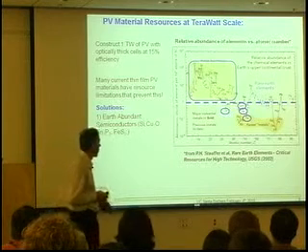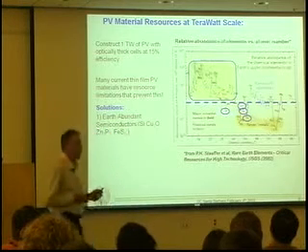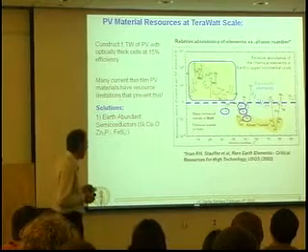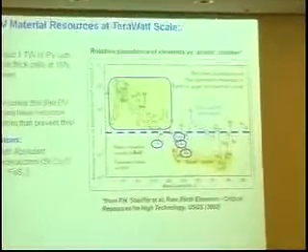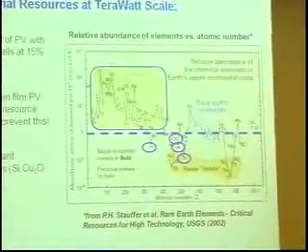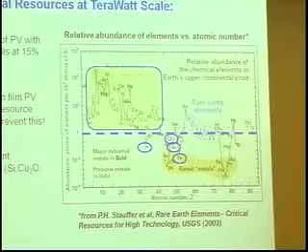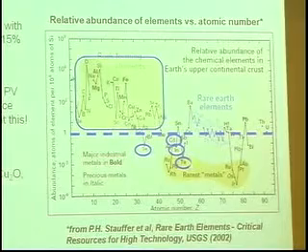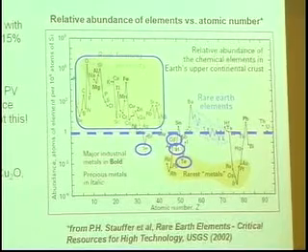There hasn't been a technological incentive to develop these materials, but there are a number of semiconductor materials that you can imagine making with transition metal oxides, phosphides, sulfides, nitrides that would certainly satisfy the criterion of being abundant enough. Notice, for those of you who are compound semiconductor people, that gallium arsenide actually is above the bar for a terawatt. That's good news for you if we work on III-Vs. Indium gallium arsenide and indium gallium nitride is a problem.